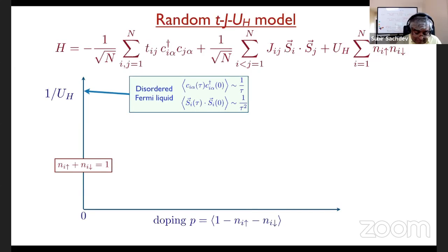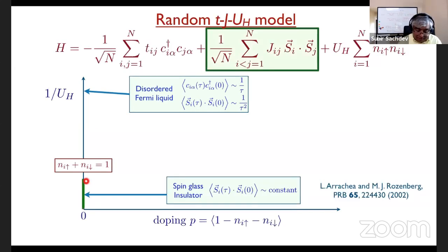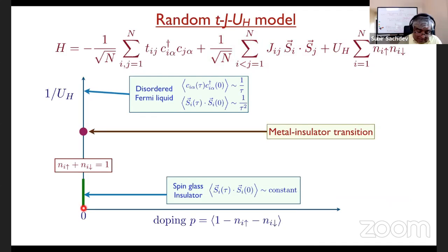What about at very large U? Well, we've also talked about that. That's the pure J model, and that was the work of Arrachea and Rozenberg, and we saw a weak spin glass order present there. And this is an insulator because now there's single occupancy per site. So the simplest assumption is that in between there's a metal insulator transition.